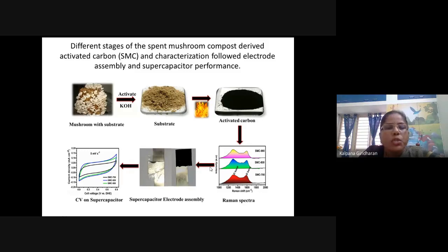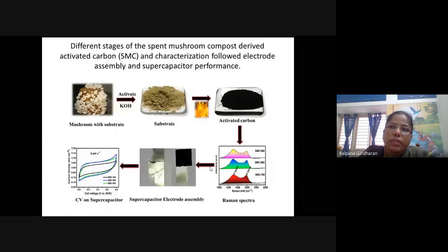It is well moistured and very fibrous. After collecting it, we washed it very well and dried it in sunlight for more than 24 hours, then crushed it with a mixer. This is the substrate we got.